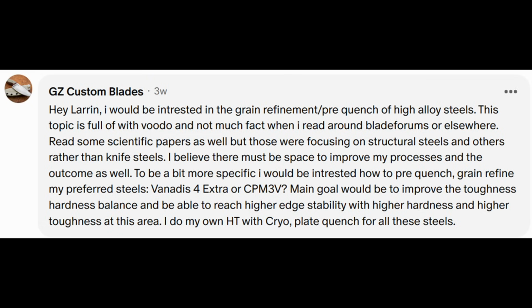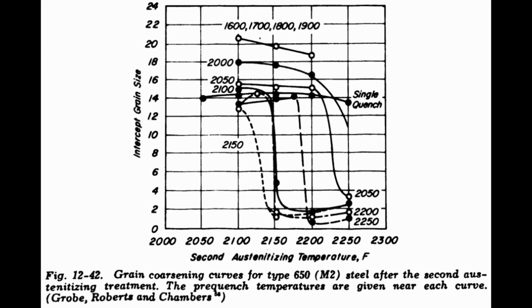To be more specific, I would be interested how to prequench grain refine my preferred steels, Vanadis 4 Extra or CPM 3V. Main goal would be to improve toughness, hardness, balance, and be able to reach higher edge stability with higher hardness and higher toughness at this area. I do my own heat treat with cryo plate quench for all these steels. Okay, first of all, what is prequench?